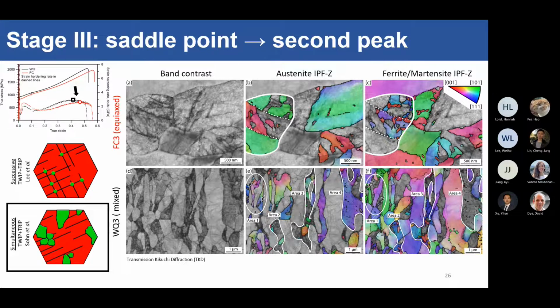In the water quench sample, it's a bit trickier to see, but again, I've highlighted some areas in white, and you can see, within this grain here, again, you see martensite grains starting from the grain boundary, then they're working their way in. So to summarize again, both of these steels have a very similar martensite nucleation and growth mechanism.